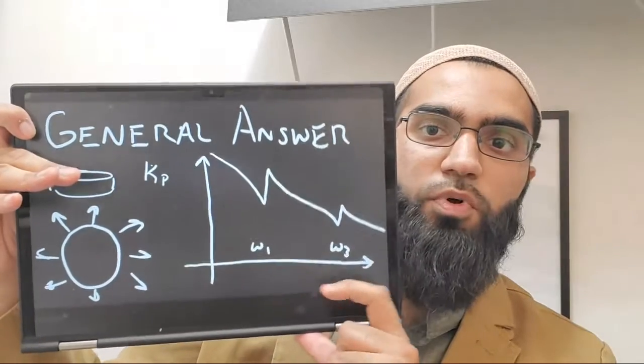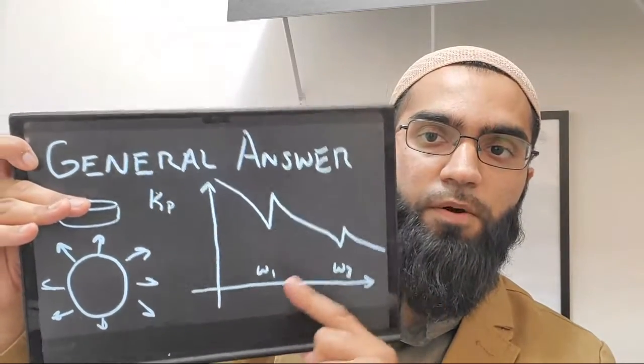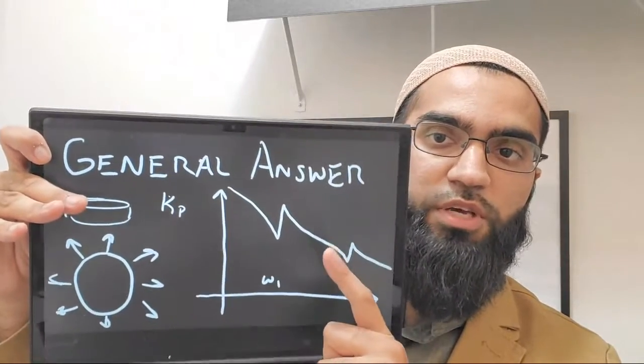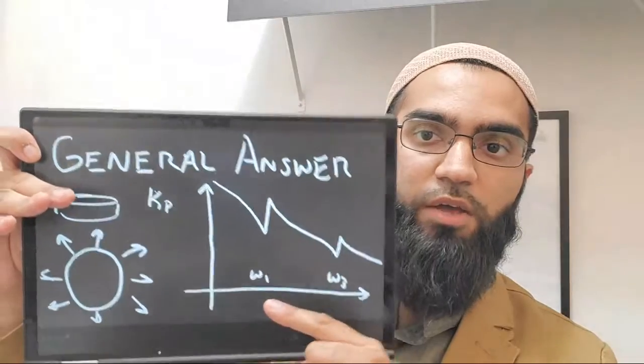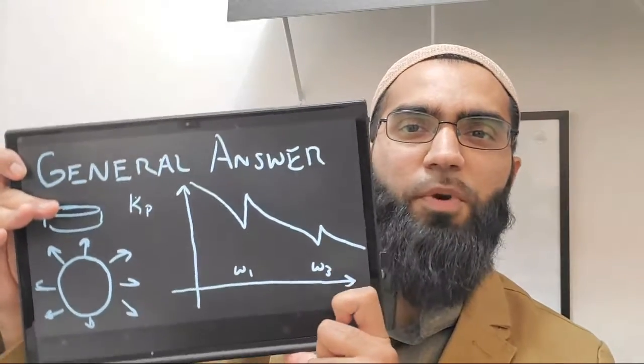And we have multiple resonant modes, and they occur in odd numbers because of the symmetry of the device. You won't see an even harmonic. You'll see the first at a given frequency, and you'll see something around the third, but it won't be exactly 3 times higher. And there's so much magic in this because there's an extra mechanical contribution to your planar resonator that doesn't happen in a rectangular shape.